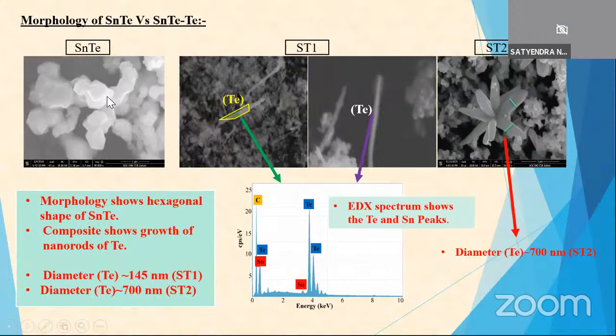This is the SnTe system, which shows the hexagonal phase of the morphology, and this is the growth of the nanorods, which is enhanced as the temperature is increasing. So there is the enhancement in the growth of the nanorods, and the SnTe seeds are predominantly present in the system here. So this reflects enhancement of the thermal power also. So this is the EDX measurements spectrum. So this shows the growth of the tellurium nanorods in the axis.